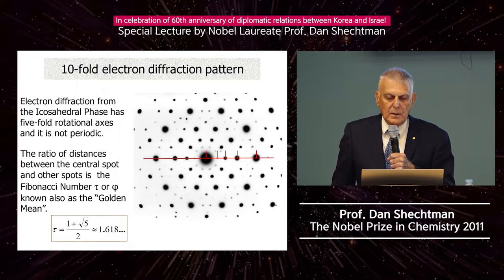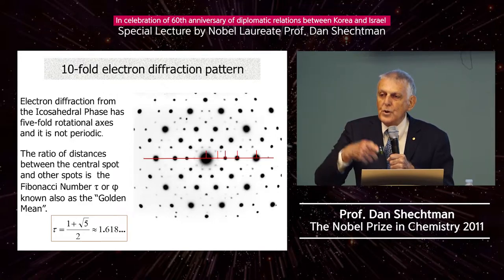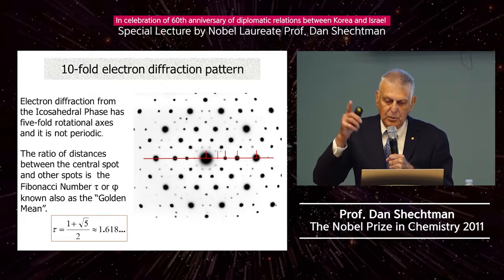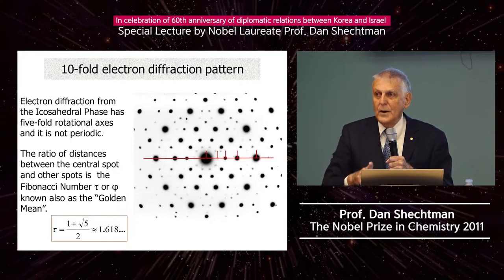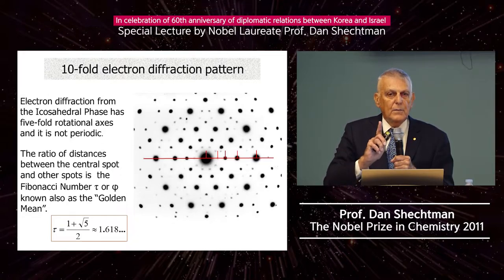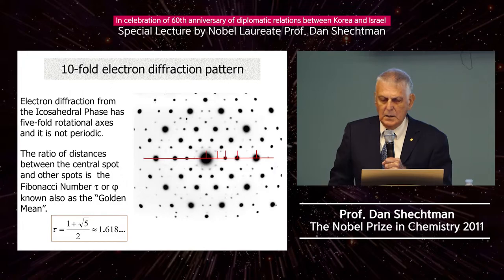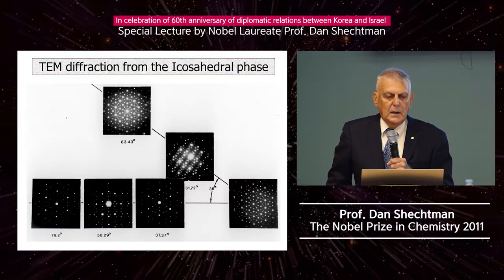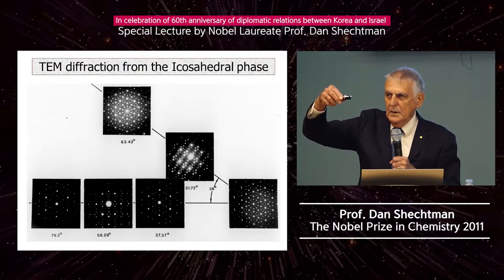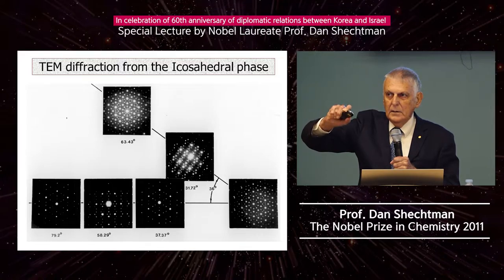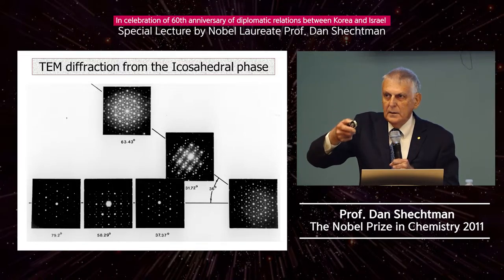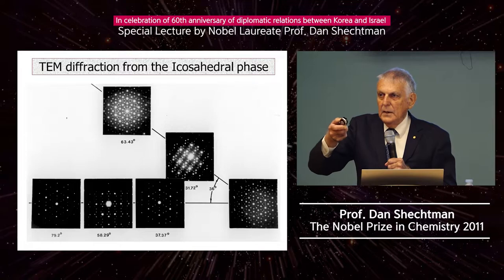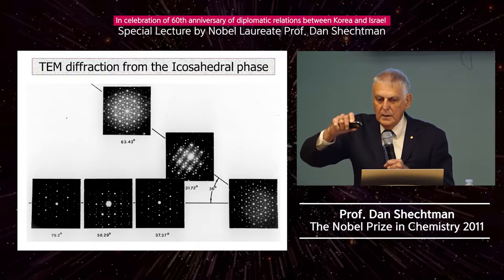So this was the surprising diffraction pattern. By the way, this is the original pattern. I took many more later on, but this is the original one. Look at the quality. It's very, very high quality electron diffraction. Now, this diffraction pattern was not the only one. If this is a specimen, I can tilt it and rotate it in the electron microscope and have diffraction patterns from all angles.